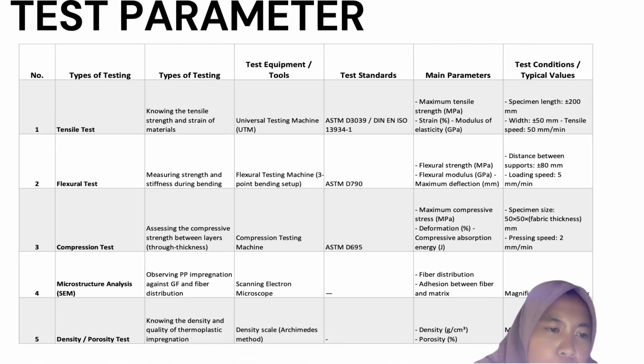For microstructure analysis, test observing polypropylene impregnation and glass fiber distribution, using scanning electron microscope; parameters: fiber distribution, adhesion between fiber and matrix. Five, density or porosity test. Knowing the density and quality of the thermoplastic impregnation; parameters: density in gram per cubic centimeter, porosity in percent.